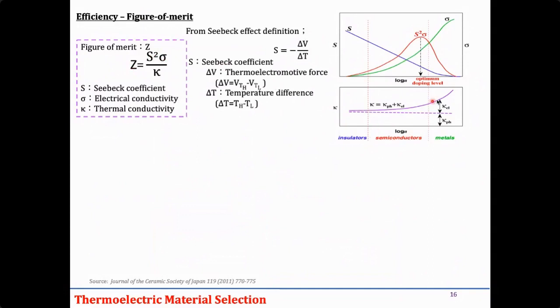So what are the ways to decrease kappa? First, there are two phenomena. When we try to decrease the thermal conductivity of the electron, it will disturb the electrical conductivity and the Seebeck. That is why people focus on the phonon tracking effect, the phonon-electron interaction. With the help of that, the thermal conductivity can be decreased through the phonon, making it very low without disturbing the electrical property and the Seebeck coefficient. So that is a way.